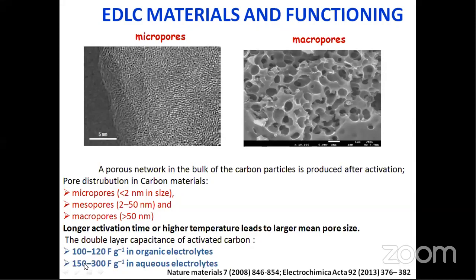But in the case of aqueous electrolyte, you can still get 150 to 300 farad per gram, at 20 millivolt per second or 1 ampere per gram, when you test that material. So that's why I always prefer the aqueous electrolyte.